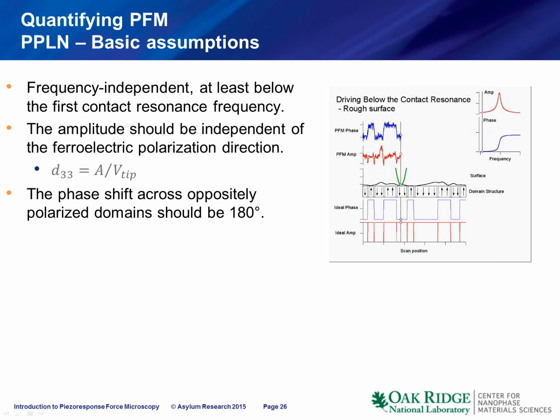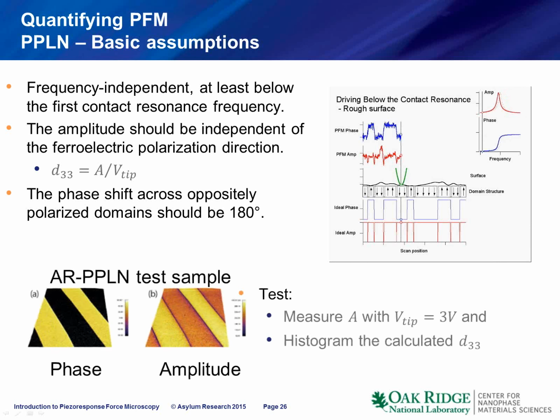causing a frequency shift. Our sample, as I mentioned, was this periodically poled lithium niobate. This is fairly typical phase and amplitude measurements on it. The test I'm going to tell you about right now is that we measure an amplitude of the cantilever with a given drive voltage at about 40 or 50 kilohertz. We then calculate the D33 with this equation here, and we're going to make histograms of that D33. We did it with AC240 cantilevers, 10 of them, over the same PPLN sample, so there could be some spatial variation, but we don't expect it to be very much.